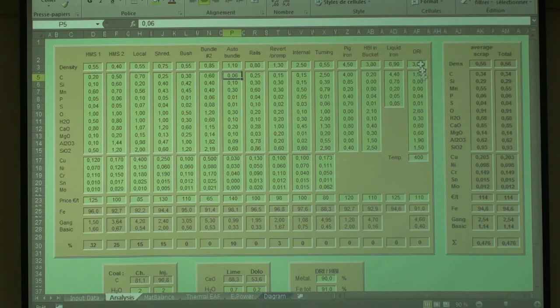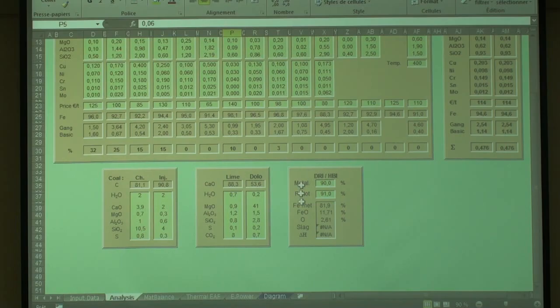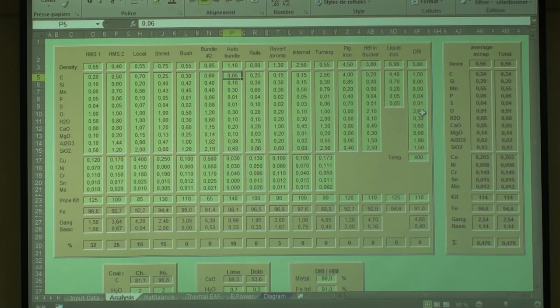Then we have seen that also DRI is provided here with a small calculation table to calculate the amount of oxygen in the DRI. This oxygen is very important because it costs a lot of energy. In case you are using a huge amount of DRI or HBI in the furnace, you are obliged to reduce this iron. Yeah?